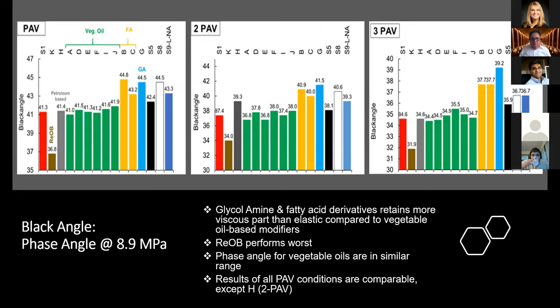The phase angle of 8.9 was chosen because it relates to the new proposal to AASHTO to increase the G* sin delta limit to 6,000 kilopascals in the AASHTO M320 and M332 specifications for binders having a phase angle of 42 degrees or higher. This phase angle was shown to correctly rank samples based on their ability to relax stresses and is insensitive to the grade of asphalt being tested.